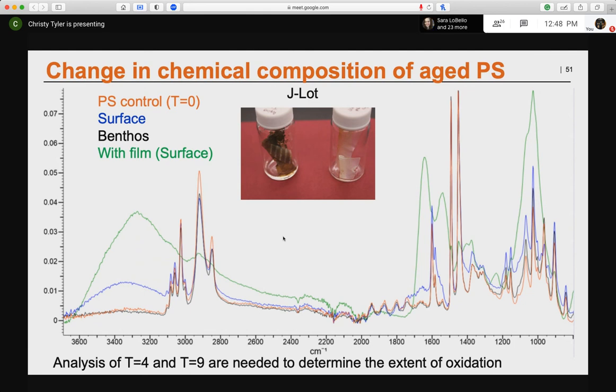And truthfully, this large adsorption of this biofilm might be one reason why we're seeing less toxicity in the JLOT than we did in Ontario. Because if we have this film being formed, the organisms might not be as exposed to the plastics. So that might be some reason. And like I said, this is by far the strongest adsorptive film that we have observed from all these species. So that's, like I said, a lot of preliminary data.